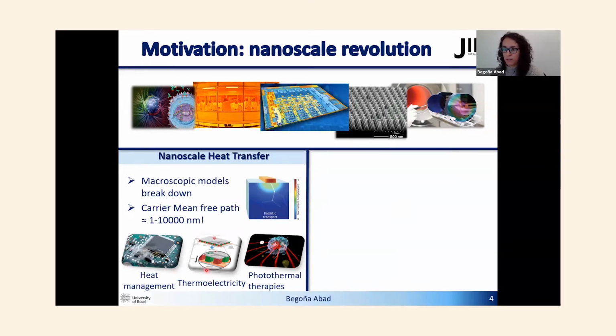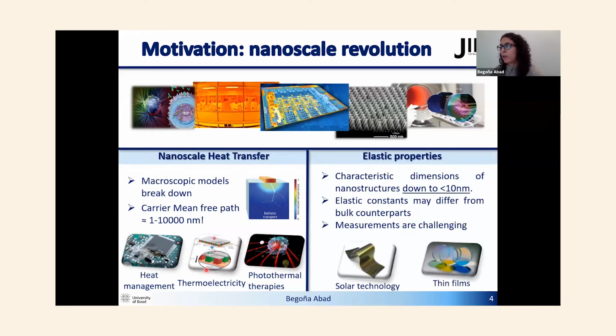thermoelectricity, or photothermal therapies. On the other hand, my work was also focused on the study of elastic properties. And here we want to characterize dimensions below 10 nanometers because the elastic constants sometimes differ from the bulk counterparts. In this case, for example, a thin film below 10 nanometers is extremely difficult to characterize because it's really difficult to decouple the properties of a thin film from those of the substrate.